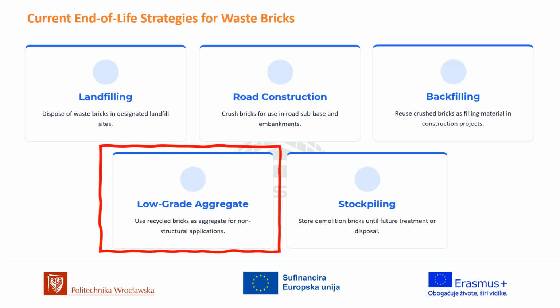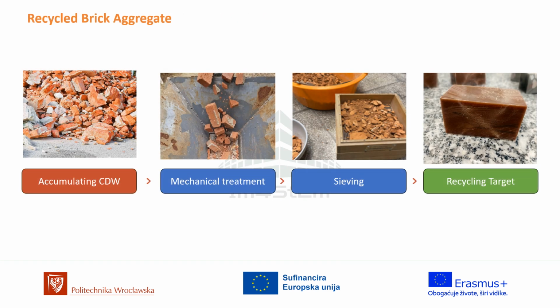It can be done by using waste brick as aggregates, not always low-grade, but as a promising alternative to the natural ones. How can we implement this approach? The process must begin right at the demolition site. With selective dismantling and rigorous material sorting, once separated from contaminants like wood or other organics, the brick waste undergoes mechanical processing using heavy crushers and industrial sieves. This allows us to process dirty rubble into clean, well-graded ceramic aggregate, or fine brick powder with precisely controlled particle size. Then we can move further to integrate it into various composites.